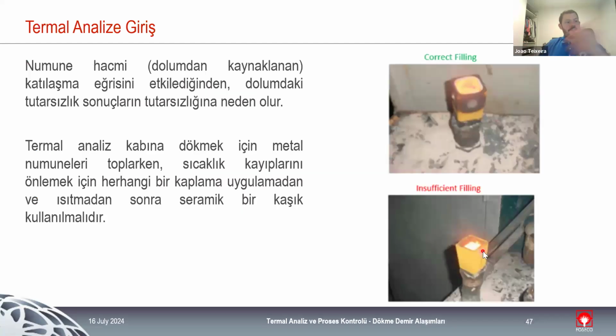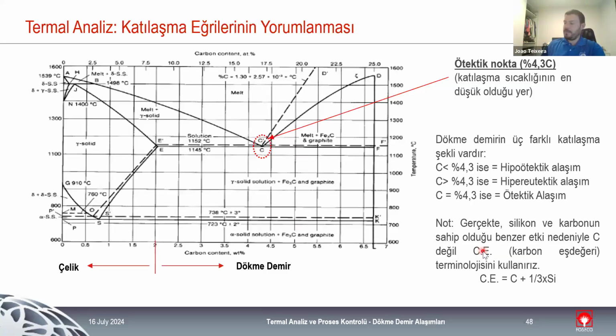This is just to illustrate the differences between the correct filling and insufficient filling. Being a small sample, it is really important to always have the same amount of liquid metal in the cup, because the readings can differ if different amounts are present in the cup. It is based on the position of the thermocouple, and it is based on the total volume of liquid metal that is solidifying in the cup. So it's always important for us to have a correct filling every single time.